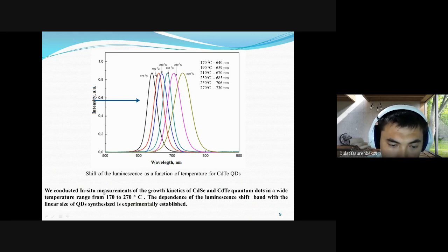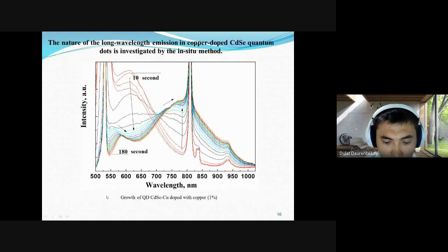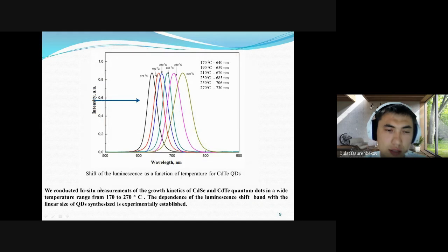By in situ measurements, we investigated the growth kinetics of cadmium selenide and cadmium telluride quantum dots in a wide temperature range, because temperature is the main parameter which influences their size distribution, and where you can see their luminescence. It's the main parameter, and we studied it. And now we know exactly at which temperature and for which quantum dots it's characterized, with a constant concentration, of course.